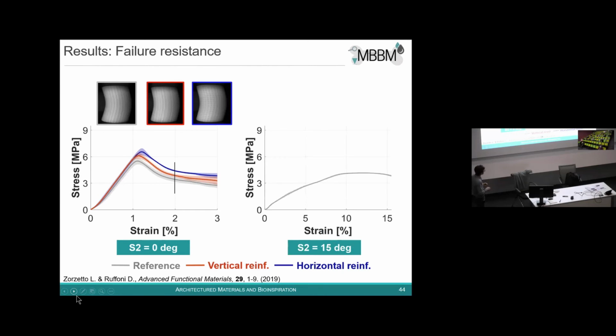What is interesting is what happens when we do the same exercise, but now the main fibers have some angle. And here I present the result of 15 degrees, for example. At a 15 degree angle, well, we have a system which, first of all, does not show a big failure, or let's say catastrophic failure, as the straight fibers.